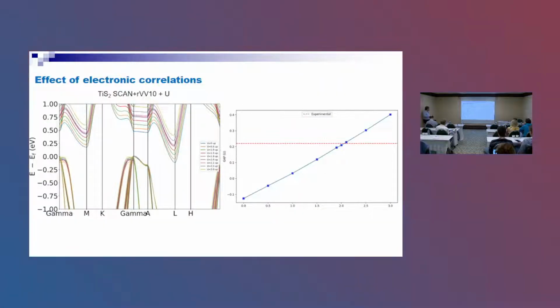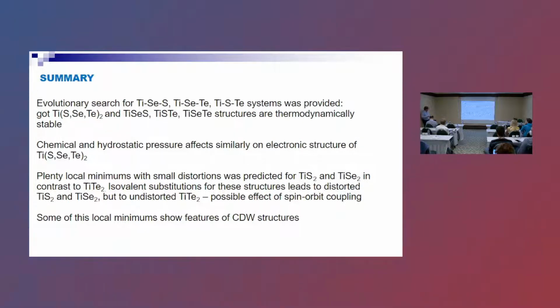Let me skip and come to the conclusion. Basically, what we found is that already on the level of DFT, very similar, isovalent materials are very different. Some of them can have a metastable state, some of them do not. And probably, if we include multi-particle physics, it will give us a true triple Q state, which we see in the experiment. That's all I wanted to say. Thanks.